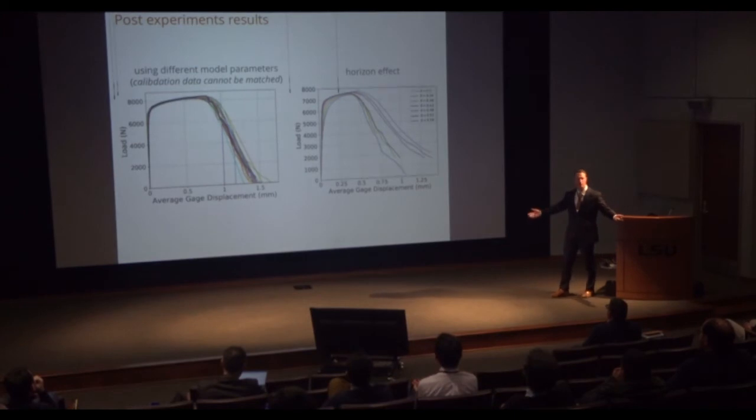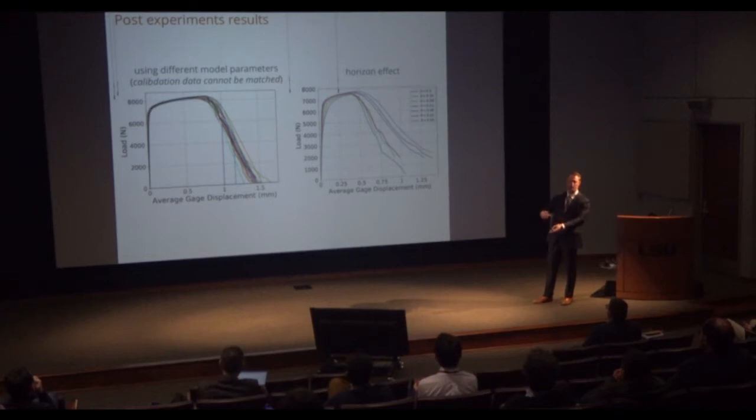Now that I have the results, no problem. I go in there, I put the resulting calculations into our optimization framework, solve the inverse problem, and I can match everything perfectly, right? So having known the results, it looks great, right? And of course, there's a lot of parameters to play with here, because you have this transition from plastic strain to damage, and when that critical failure occurs, the damage model parameters come into play. If you have all of those parameters to play with, you can fit this perfectly. Now, of course, this is meaningless because the elastic modulus is like twice the real elastic modulus of the material. Or not twice, but it's significantly different. As well as, if you were to take the parameters that you used here and go back to the calibration data, you wouldn't be able to predict those correctly.